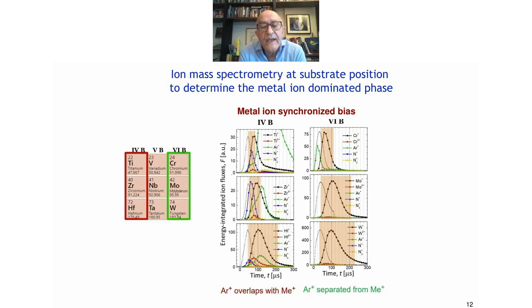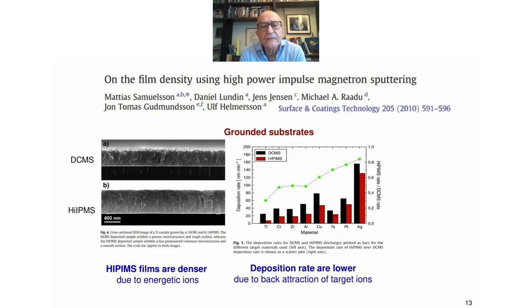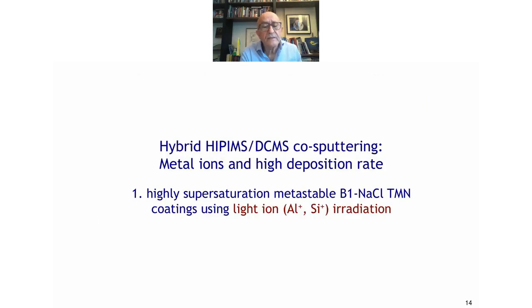So the next slide illustrates how this data can be used to select the metal ion assisted growth. Next slide. So this is one of the earliest papers by Helmersson, showing that because HiPIMS produces energetic ions, even on a grounded substrate, it is capable of producing dense films. And on the right, you can see that the cost of this is that the deposition rates are lower, because of the back attraction of the positive metal ions to the target. And this is for all targets. Next slide.